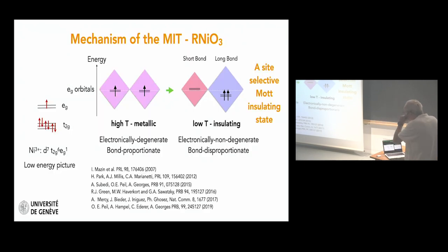So the picture is a high temperature metallic state, which is here, electronically degenerate, bond proportionate, and you turn into a low T insulating state, non-degenerate, and bond disproportionate. And then the system turns insulating, and some people talk about a site-selective Mott insulating state.